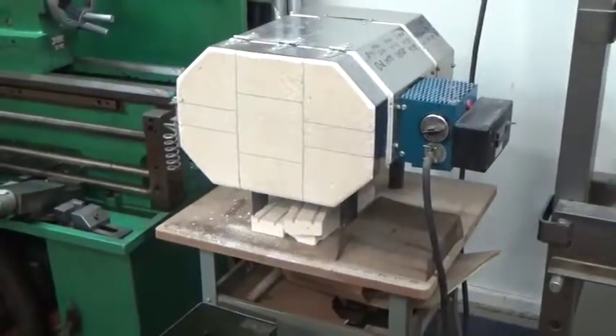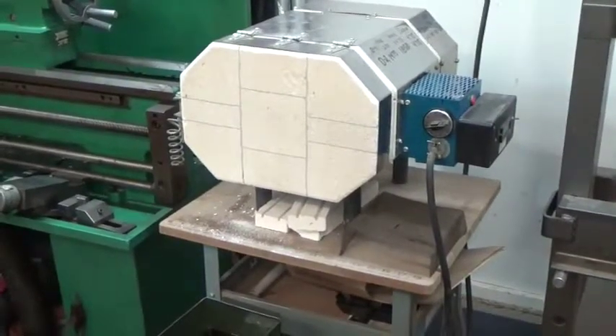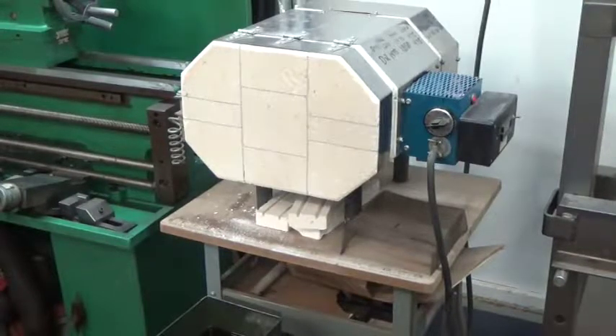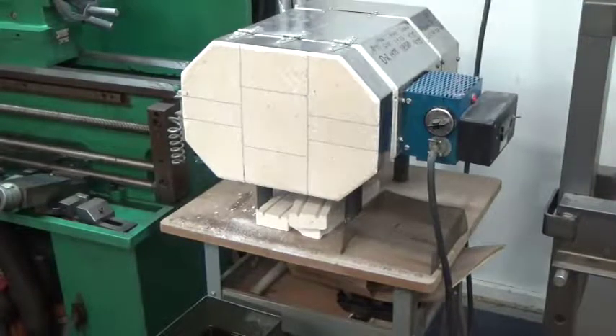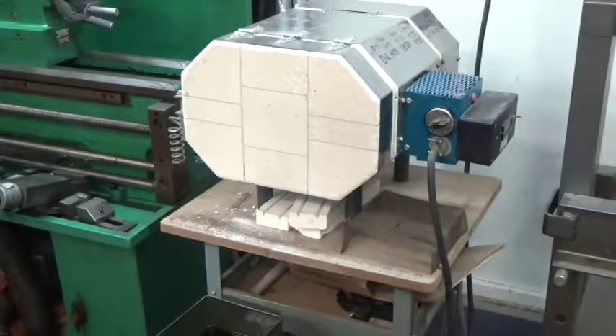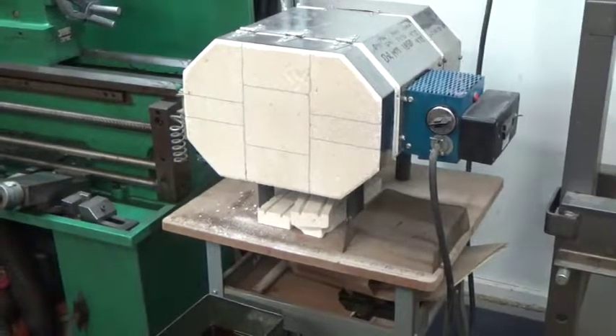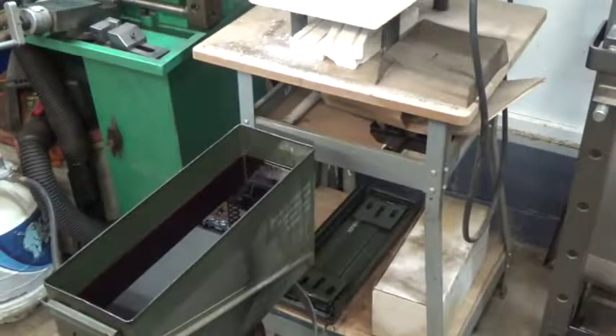Okay, the blade is at 1400 degrees now, so we're going to hold it there for just a little while. It's thin in cross section, so it won't take long for it to normalize at that temperature. And then we're up to 1900. You know, with the exception of the oil quench, the process is very similar to the heat treatment I do on D2 steel. D2 is just quenched in air, also in the foil.